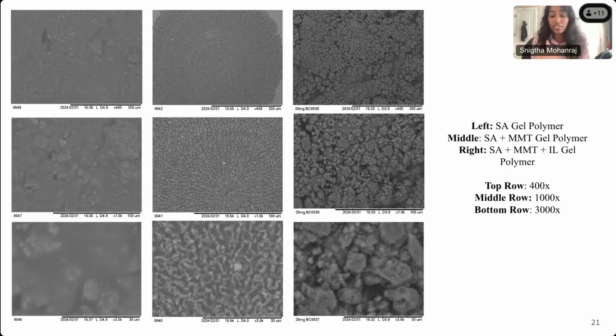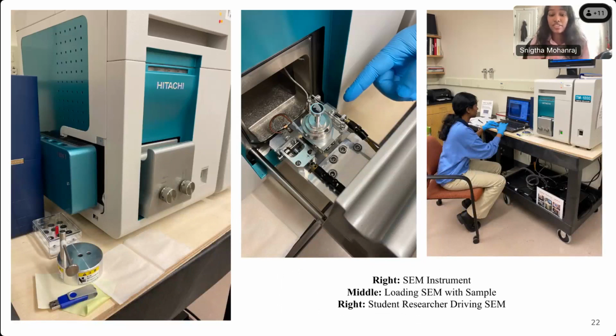And when we look at just the sodium alginate, MMT, and IL column on the right, with the increasing magnifications, we can see it's very rough, it's very textured. There's a lot of pores, making it very ideal to be using. And these pictures just showed the SEM instrument and me driving the SEM. I just thought they were cool to include, so here they are.